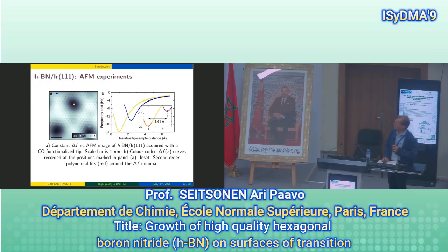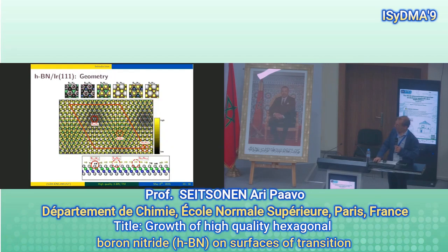So this is the moiré of hBN on iridium. It's just some curves along at the same position laterally, but different heights, and they could derive the height of hBN at different positions of the moiré.